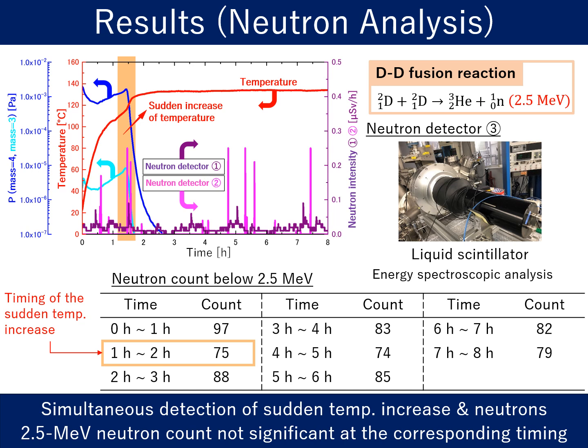For the neutron detection results, we simultaneously detected neutron intensity peaks from 2 independent gas proportional neutron detectors at the coincident timing of the sudden temperature increase. Then we carried out energy spectrometry by using liquid scintillators with a great technical support by Professor Honda and Professor Kasagi of Tohoku University. The neutron count around 2.5 MeV at that specific timing was unfortunately not significantly larger than other time regions.